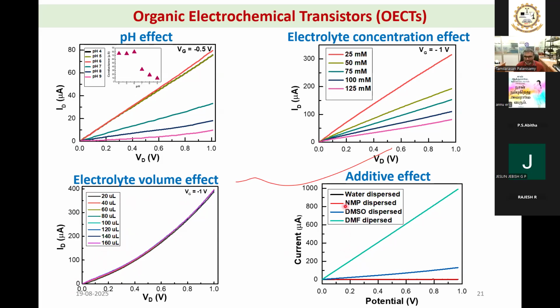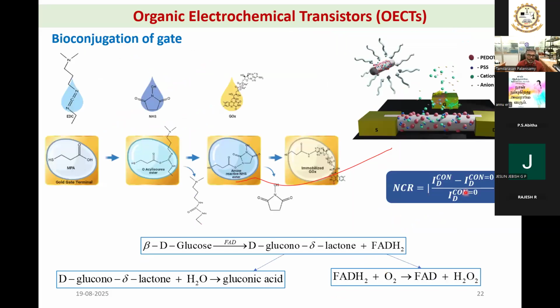On the other hand, we have also checked the effect of additives, because when we coat PEDOT:PSS, we put different additives. So we found that the DMF dispersion gives a better conductivity. So we generally use it during coating purposes. All right, so we have fabricated the sensor. We have completely tested the sensor at different conditions as well. Now the OECT has shown a very good capability to use it as a sensor.